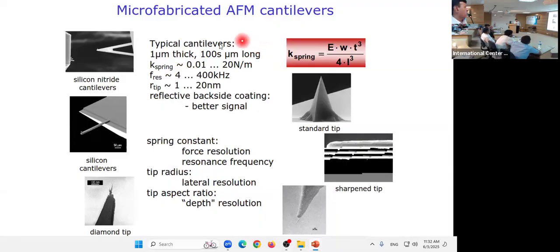And that resonance frequency changes if there is any kind of dip. Normally, the radius of the tip ranges from 1 nanometer to 20 nanometer, and this depends. There are advantages and disadvantages of this tip. Advantage, if you are using a thinner tip, is that you will get an image of very good resolution, even at the resolution which you can get with the scanning electron microscope or transmission electron microscope.